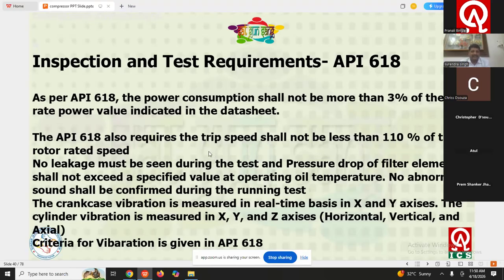Another requirement given in 618 is that the trip speed of the compressor shall not be less than 110% of the rotor rated speed. So if I am declaring that my compressor rated speed is 1000 RPM, my compressor shall not be tripped below 1100 RPM. Before this, the compressor shall not be stopped or tripped. Otherwise, the test result will be on the failure side, and you will give remarks that the test did not succeed.